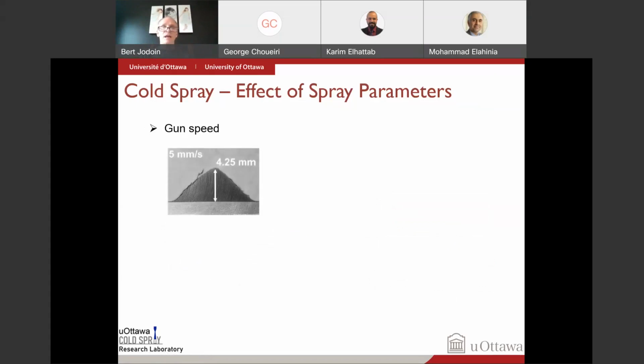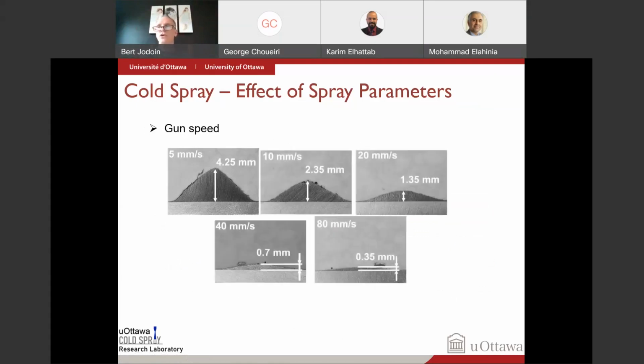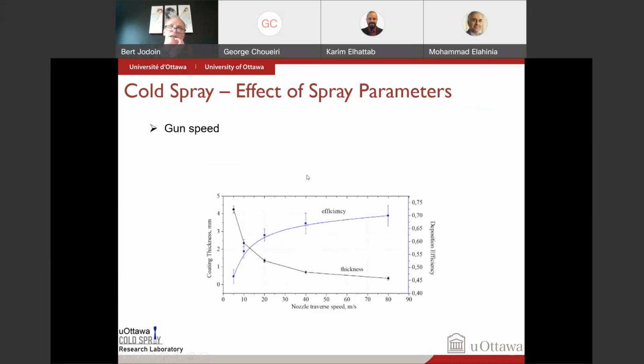The gun speed, as you increase the gun speed, so that's a coating of 4.25 millimeter when you spray at 5 millimeters per second, that's your gun speed. If you increase the gun speed, of course, your coating decreases in thickness, but look, it doesn't decrease linearly. See, we've doubled the velocity, but it's not half of the thickness. Why? Well, here's what you have.